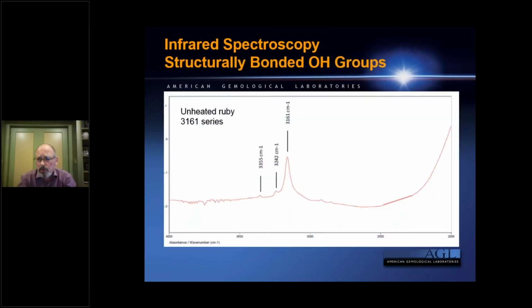There are also structurally bonded OH groups. Now, structurally bonded OH groups are something that can occur naturally in corundum, in ruby. They can also be induced or altered as a result of heating. So one which is sensitive that we're able to track is what's called the 3161 series. It's a group of bands that always seem to occur together, with the main peak positioned at 3161. This is also thermally sensitive. So if you start to see features such as this, you start to get an idea that a stone is not heated.